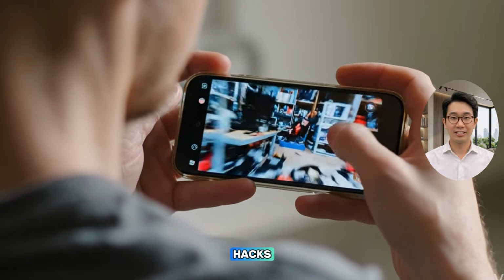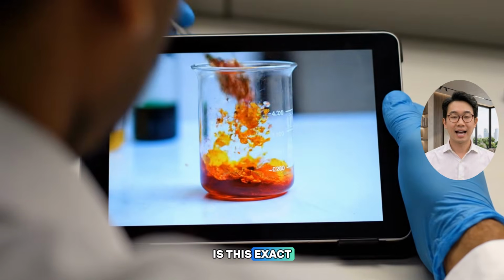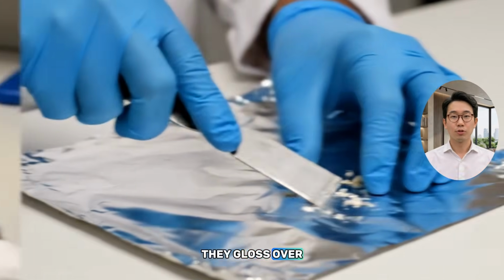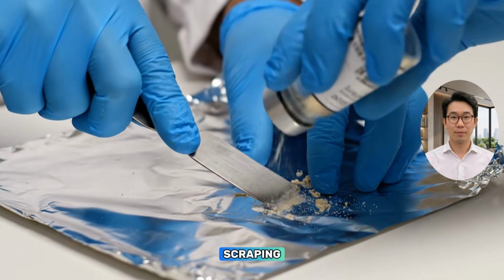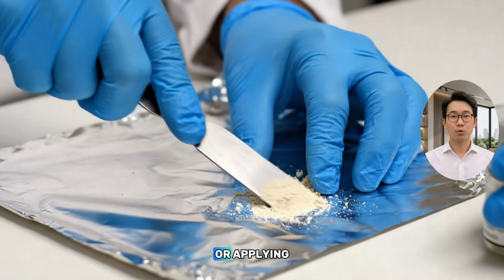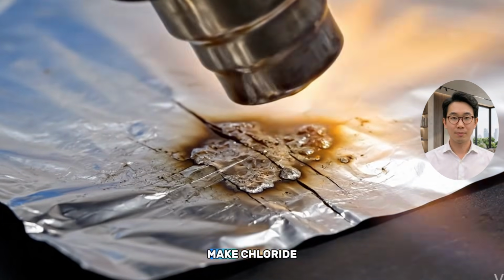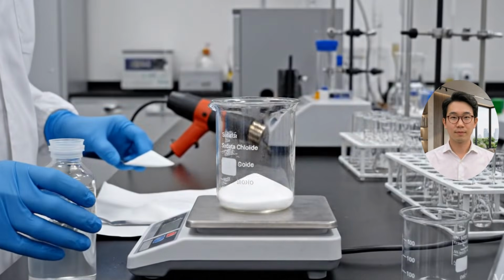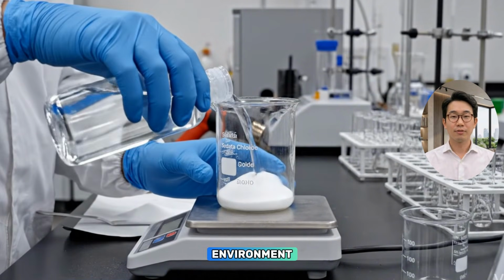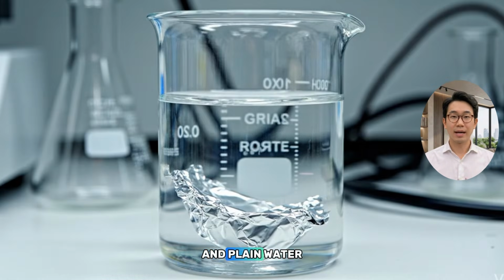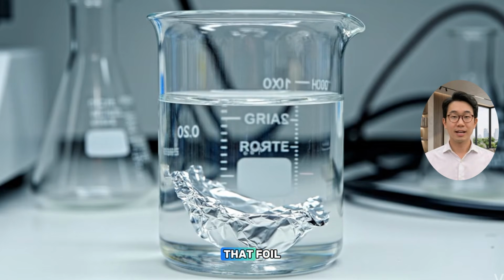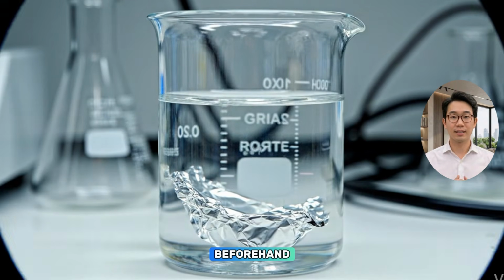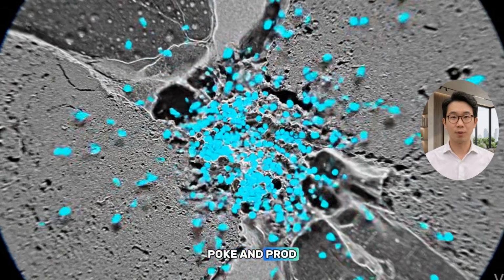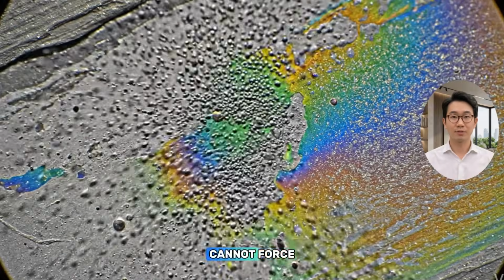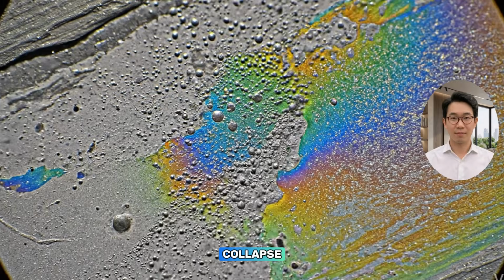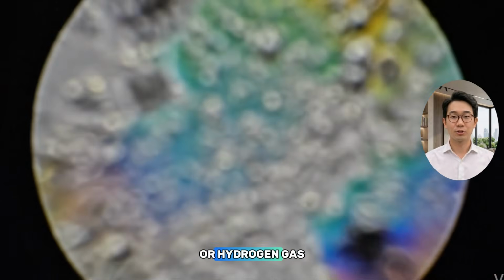What those internet hacks conveniently edit out is this exact inconsistency. They gloss over the crucial requirements, like physically scraping the foil using chemical impurities or applying high heat, that actually make chloride-driven pitting possible. If you run this in a strict laboratory environment using pure sodium chloride and plain water, almost nothing happens unless that foil has been specially treated beforehand. Chloride ions might poke and prod at the oxide layer, but they simply cannot force the catastrophic structural collapse required to unleash meaningful heat or hydrogen gas.